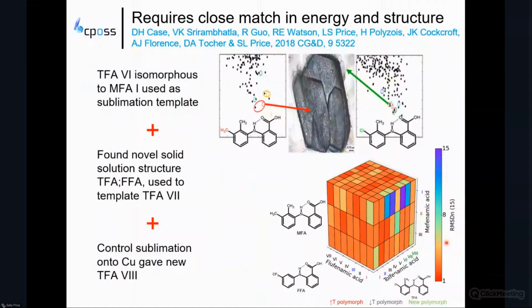It is very demanding of how close a match in energy and structure. We also looked at the fenamate family, which had been heavily studied for polymorphism. And when we started, tolfenamic acid, which has a chlorine, and mefenamic acid, which has a methyl group here, that's about as chemically similar as you can get, but they had no isostructural polymorphs until our CSP suggested it would be worth taking mefenamic acid form 1 crystals and subliming tolfenamic acid onto it, and that got us tolfenamic acid form 6 as an isomorphous structure. This is just COMPACK, which gives you how many molecules in a 50-molecule coordination sphere can be overlaid within moderately loose tolerances.